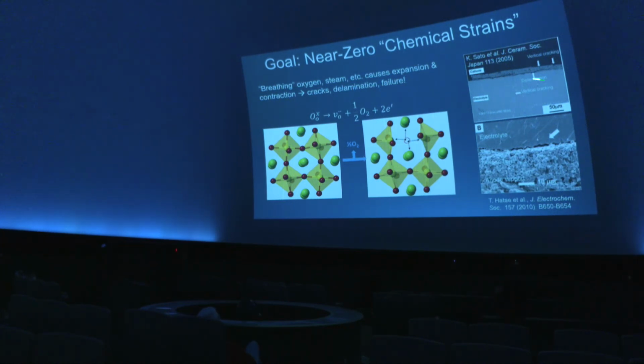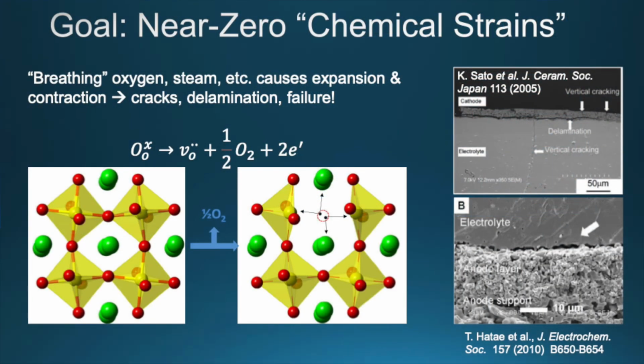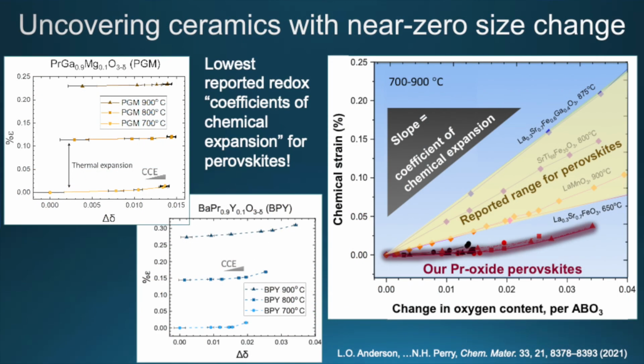And again, the problems are that it causes these cracks and even parts in these sandwich structures to separate, and then the device doesn't work, right? Because these materials are expanding and distorting as they breathe. So I'll just show a couple of examples from our lab quickly. One of the new classes of materials that we've been looking at are these oxides that have a really kind of exotic element in, praseodymium, Pr. A couple of different compositions with that. And we've uncovered these compositions that exhibit almost no size change when they breathe.